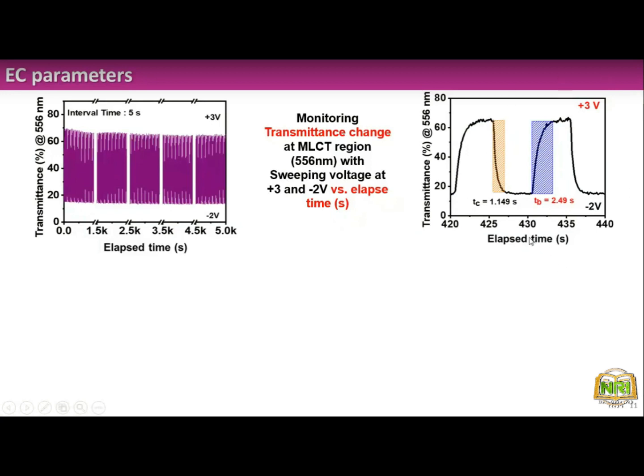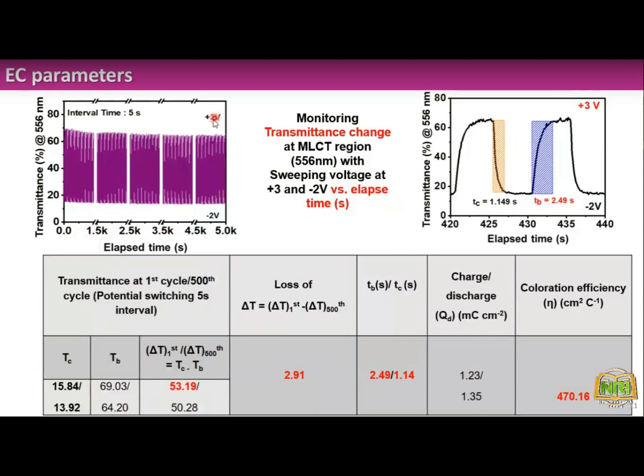So from that plot you can see, as the time is going, suppose here it's minus 2 voltage, it's colored up to a certain time I applied. As I applied plus 3 for 5 seconds, it is coming up again. Again I am applying minus 2 voltage for another 5 seconds, again another 5 seconds plus 3 voltage, and this cycle I continued up to 5000 seconds. So this is the whole cycle, and this is a zoom version of that. For understanding, I'll just come to the parameters. We can see that Tc is transmittance at the color state, this particular transmittance value, and Tb is transmittance at the bleaching state. The difference between these will indicate the change in the optical contrast.